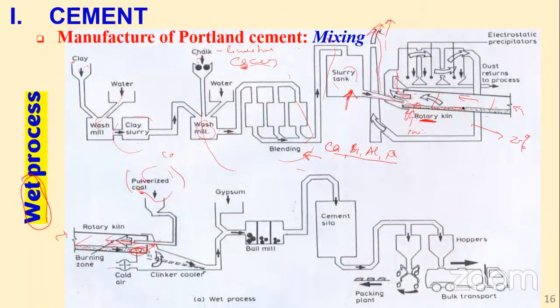So as the slurry moves down, the moisture is driven off and carbon dioxide is liberated. Then as it moves down, it becomes dry. At the hottest part near the bottom here, the material is liquid. Now the elements have melted, and lime, which is calcium oxide, silica and alumina combine. So this part is where fusing occurs: calcium, alumina, and silica, which is silicon dioxide.